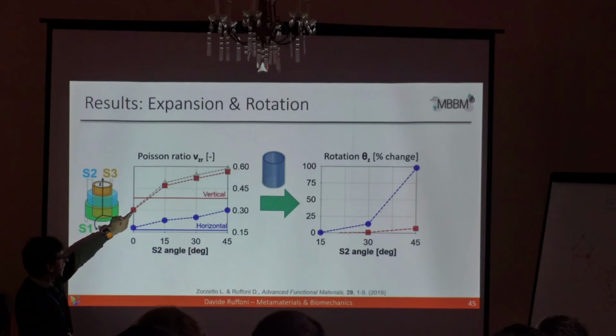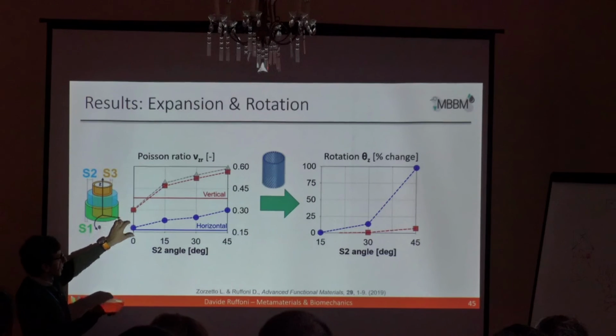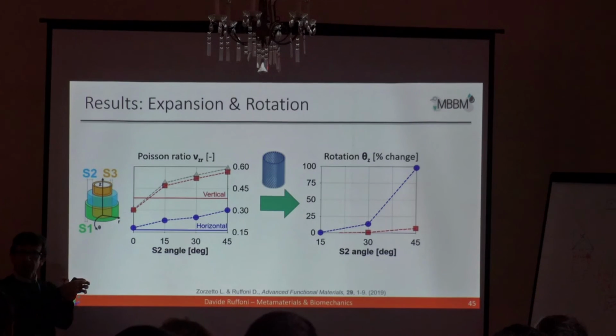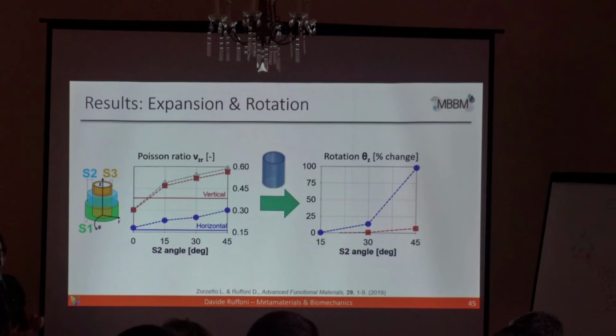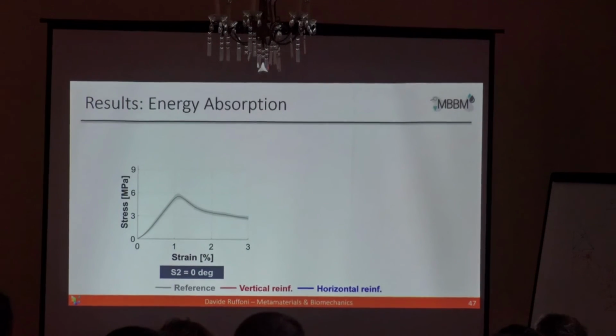And if we add vertical reinforcement, this does not change. But of course, if you add horizontal rings, horizontal reinforcement, you are basically blocking this expansion. So this is intuitive, and here we quantify this a little bit. But at the same time, when you are blocking the lateral expansion, you are increasing the rotation of the system. This is something that we had some insight on the behavior. And then we did the compression test, and these are the last results that I'd like to present.